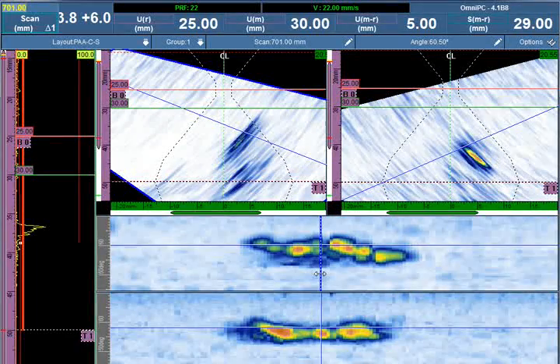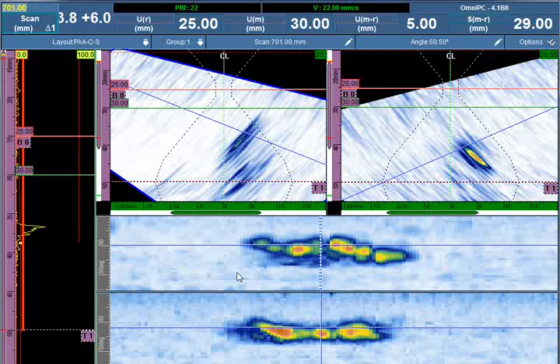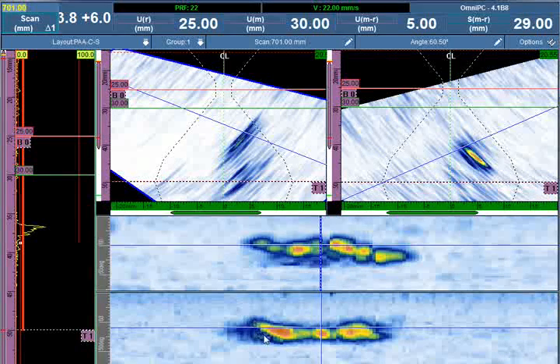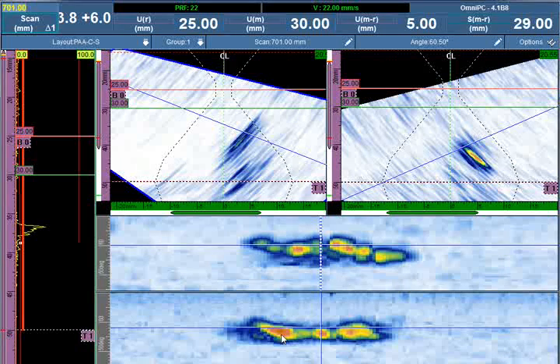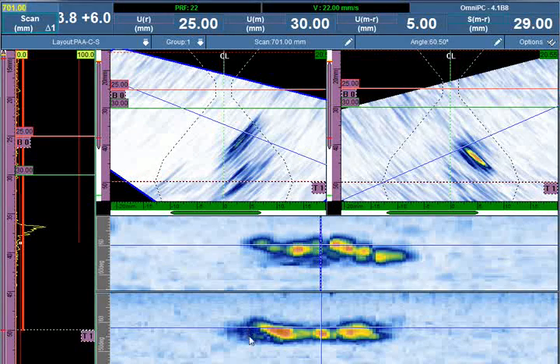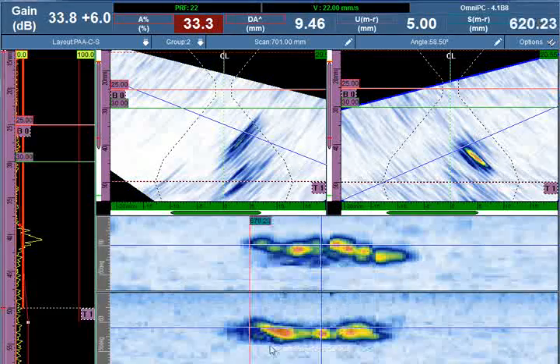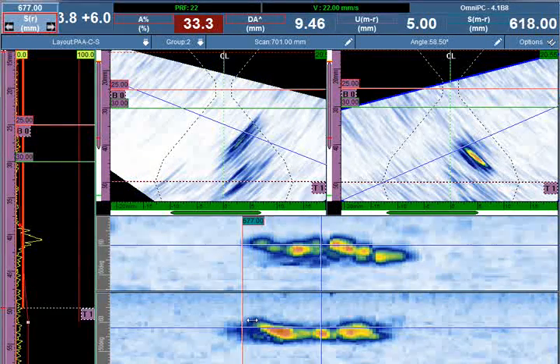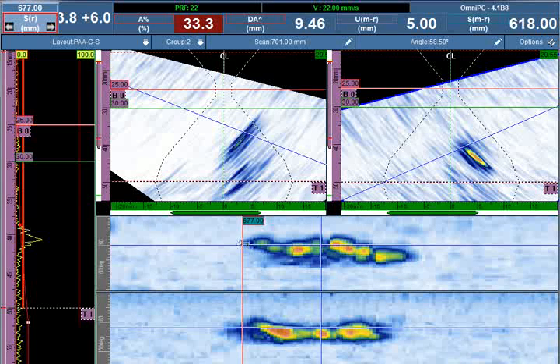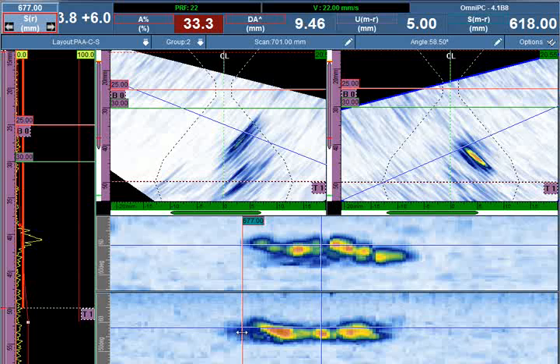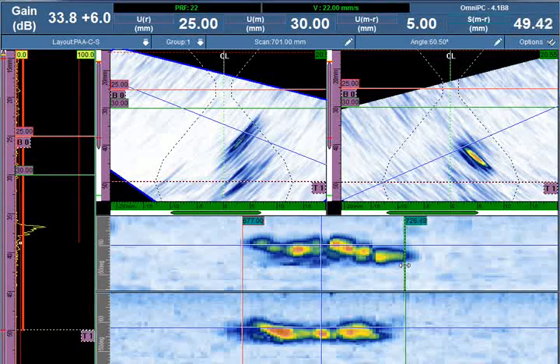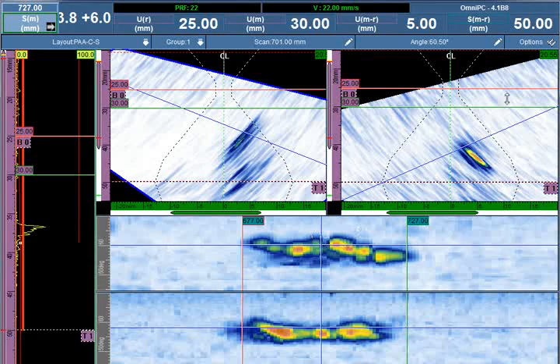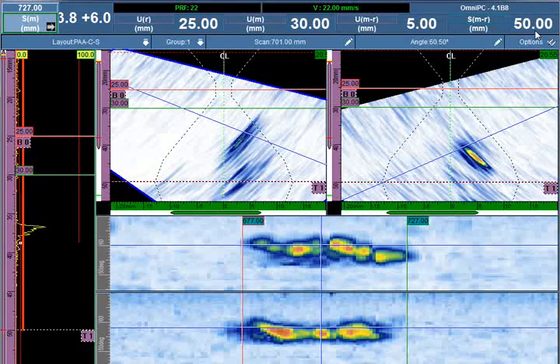Length sizing, regardless of flaw type, is determined on the C and B scan using, in this case, a rapid drop technique. Because as the flaw changes depth, height, and orientation, it has no relationship to the maximum amplitude determined as we mark the extremities of the flaw. We'll place one cursor at the extremity on one side — in this case it was detected differently by both probes — and we're going to use group 2 to identify the start of the crack, and group 1 to identify the stop position of the crack, for an overall length of 50 millimeters.